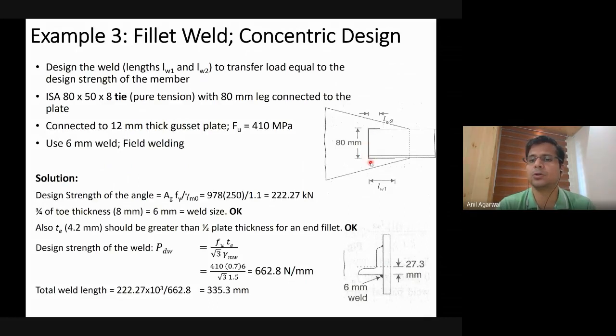Let's check. So here the angle thickness is 8 mm. 8 minus 1.5, because this is a square edge. So 8 minus 1.5 is 6.5. So the weld is smaller than 6.5. That is a good thing. So in this case, 2 mm is visible, but only 1.5 mm had to be visible. So that is satisfied. On this edge, if you see, it's 8 mm, and 1/4 of 8 mm is again 2 mm. So 2 mm should be visible and 2 mm is visible. Okay, so both these requirements are satisfied. So 6 mm weld will be appropriate. We can go ahead with 6 mm weld.